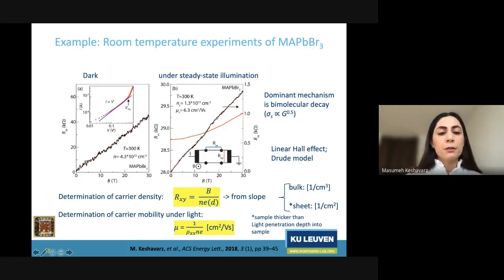So via the Hall measurements, we have access to the carrier concentration and mobility. In the dark, we extracted the mobility for the sample. On the right plot, you see the experiment which has been performed under steady-state illumination. So here the laser is on.